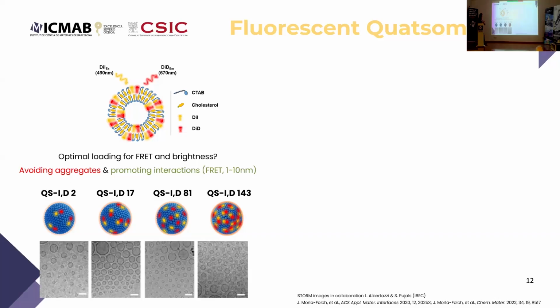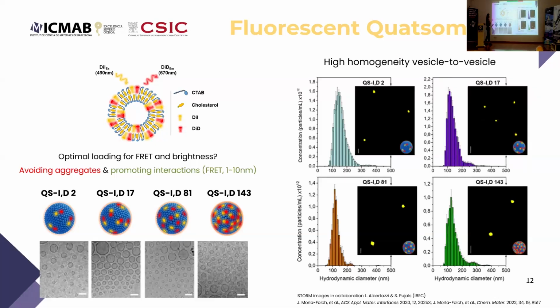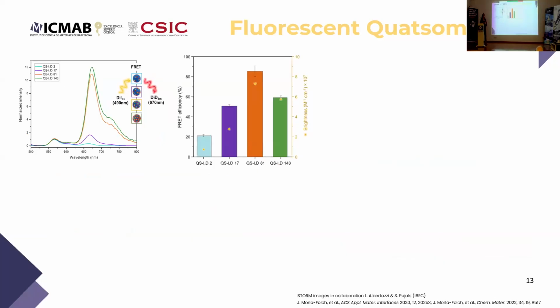So here there is the design of 4 different systems, the cryo-TEM of about 110 nanometers in that case, and the STORM images, what you see in black inside. All of them were showing this high homogeneity, vesicle to vesicle. And most importantly, in terms of photophysical properties, we were reading here the FRET efficiency once normalized to the donor, and you can see the emission of this acceptor varies depending on the loading of the nanovesicle, giving us this orange bar, the quatsome we call 81, with the highest FRET efficiency.